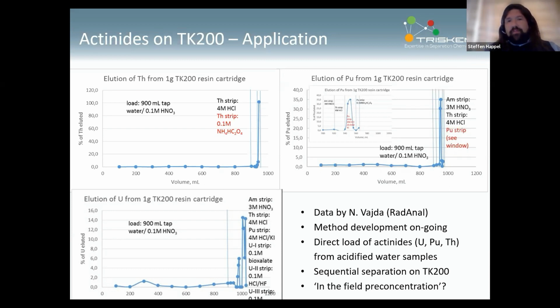actinides. So not quite there yet, still ongoing, but it is something that we find is quite interesting, and it fits also with another type of request that we get increasingly. That's the in-field pre-concentration. So basically, instead of taking a 1 liter water sample in the field, you directly pre-concentrate your sample on a cartridge in the field. And instead of bringing the water sample back to the laboratory, you basically bring back a cartridge to the laboratory. It's actually something we're working on quite a different range of applications and on not only radionuclides, actually elements. So that's generating quite some interest at the moment.